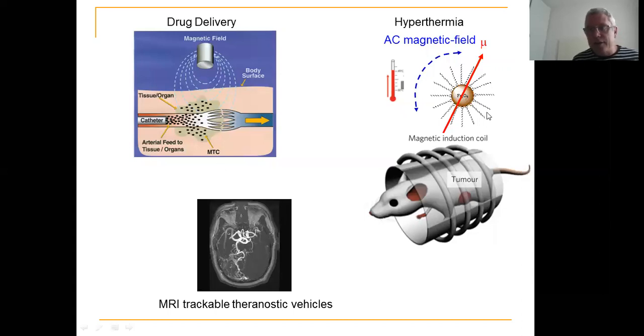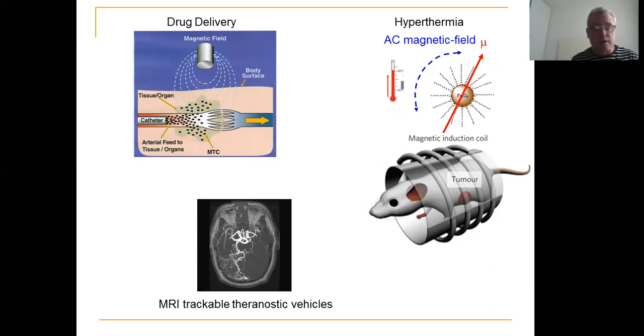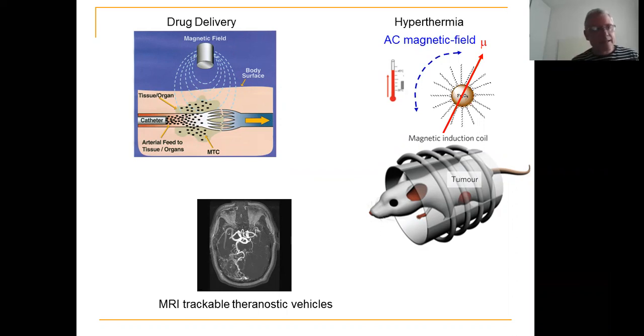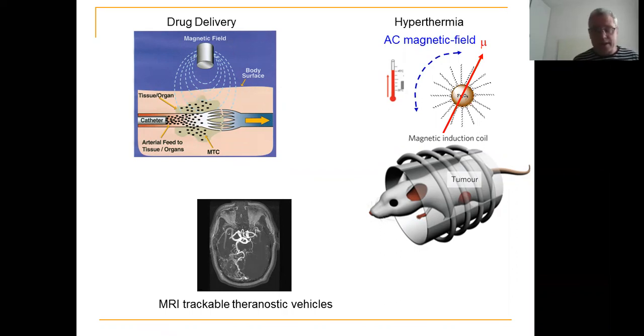If you look at magnetic iron oxide nanoparticles in the literature, you'll find a huge literature covering drug delivery, MRI, and hyperthermic responses. Hyperthermic responses occur when you put particles in an AC magnetic field in the kilohertz range — you get localised heating of the particles but not of the surrounding tissue. That can actually be used for cancer ablation, and has been done palliatively. People are also trying to apply that localised hyperthermia to deliver drugs off nanoparticles and from hydrogels. In principle, magnetisation of these particles enables drug delivery, perhaps hyperthermia, and diagnostic tracking — a potential multifunctional theranostic vehicle just from iron oxide nanoparticles.